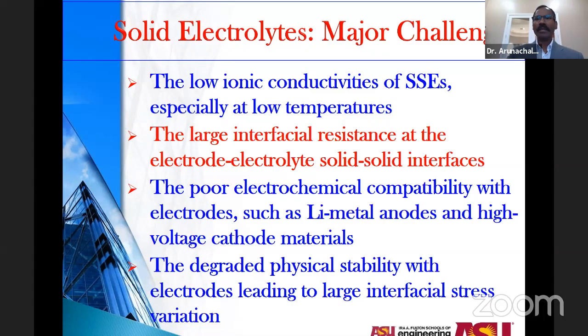Solid electrolytes, obviously, like any other product, come with a lot of challenges, which opens up a lot of research opportunities for researchers around the world. The ionic conductivities are relatively lower compared to liquid-based electrolytes, and that is mainly true when the temperature is on the lower side, at room temperature and sub-zero temperatures. One of the major issues is the larger interfacial resistance, because you have solid electrodes, anode and cathode, and also a solid sheet of electrolyte. When things are put together, it leads to huge interfacial resistance. So that's again one of the major focus areas in many research laboratories around the world.